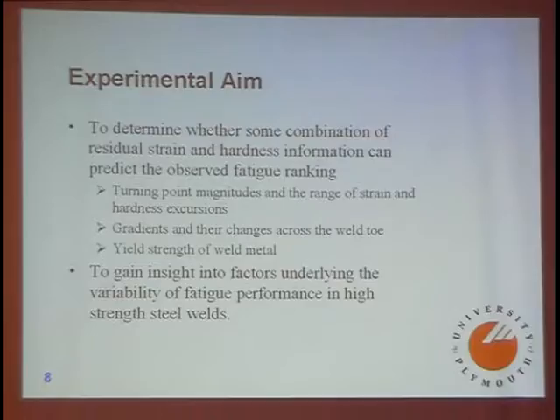So, summary of what I've said already. I'm interested to see whether some combination of residual strain and hardness information can predict the observed fatigue ranking, using things like turning point magnitudes, the range of strain and hardness excursions, gradients and their change across the weld toe, and the yield strength of the weld metal.